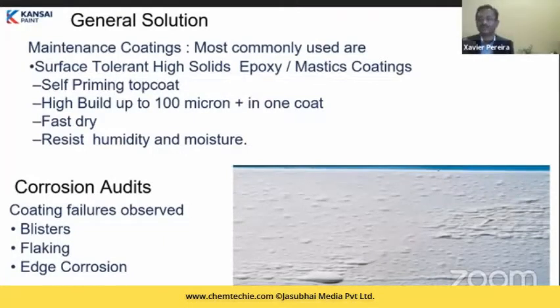So these products, while they provide you coatings at 100 to 125 to 150 microns DFT, when they are applied on rusted surfaces, they do not work. Okay, and in my corrosion audits, when I went across the country, visiting plants, the common failures which were observed during my corrosion audits have been blisters, flaking, and edge corrosion.